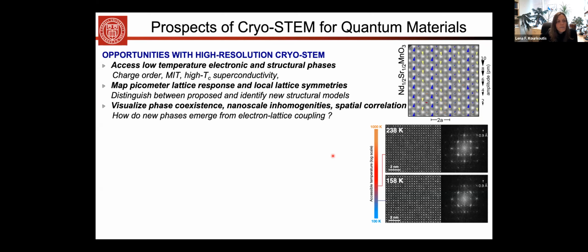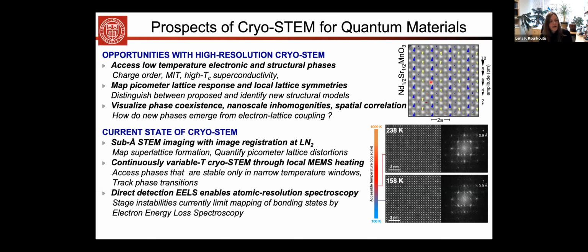With our setup, we can map local structure, you see one example here, local symmetries of the crystal. But what's more important, we not only can measure local symmetries, but also how these local symmetries vary over nanometer length scales. We can look at heterogeneities, phase competition, defects, all of the things that make quantum materials work the way they do. Where are we currently in terms of cryo-STEM measurements? I've shown you that we can measure at sub-angstrom resolution, with picometer scale precision, at both liquid nitrogen temperature and intermediate temperature through MEMS heating.